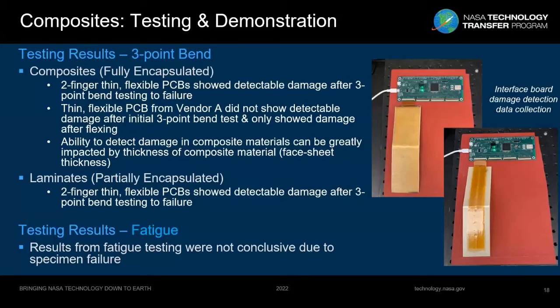In the composites, the fully encapsulated, the 2-fingered thin flexible circuitry that we attached showed damage in all cases after the composite failed, and that's what you see in the image on the right. You see where the break occurred, and that was from both vendors. However, the product from vendor A, which was the little bit thicker product, didn't really show damage until the sample was flexed. So it showed that the embedded circuitry was damaged, but it wasn't a complete clean tear. It had damaged it enough that once it was flexed, it fully separated, but it did not do that until it was flexed. The other thing that impacts this is the thickness of the face sheets.